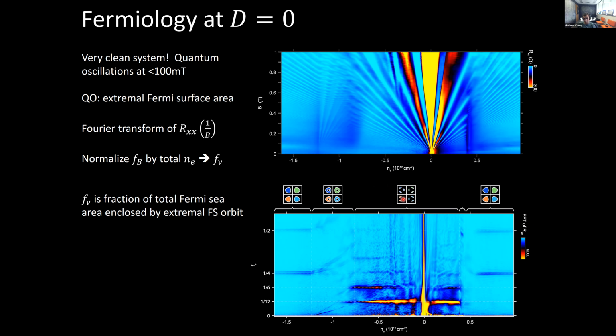So now you have 12 little Fermi surfaces related by a combination of spin, valley, and C3 rotation symmetry. And then you might have the beginning indications of a ferromagnetic state, where now you have a strong peak right around 1/2, which means you apparently have 2 Fermi surfaces rather than 4. So that means you must have broken spin or valley symmetry, and you can see there's already an indication of that on the electron side in a particular instance.